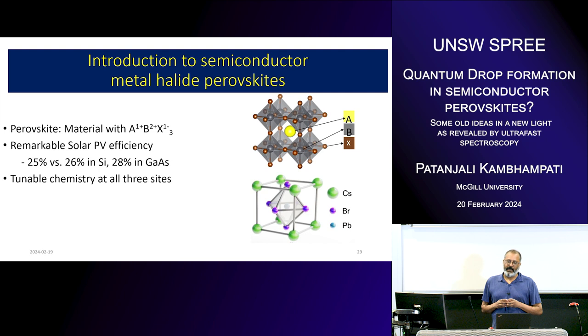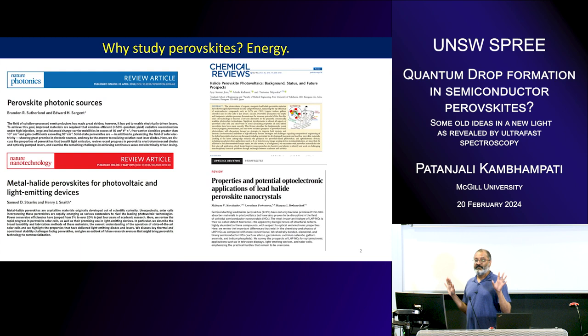The key point is that it's this type of lattice like this, with a structure within a structure, octahedral cages, and these octahedral cages are very loose and anharmonic and rattling around. There are structural dynamics that are not taking place in silicon or cadmium selenide or gallium arsenide.